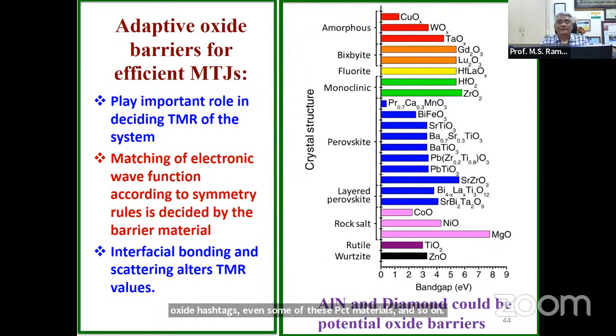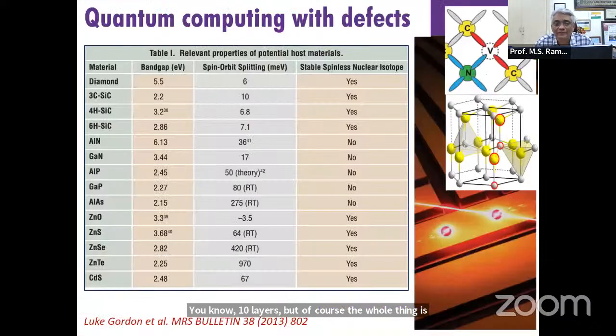This has also led scientists to think about using non-oxide layers like aluminum nitride and diamond as potential barriers. This prompted us to take up work on diamond, but it's a very, very challenging thing. While you grow oxides using a technique called laser deposition, diamond requires much higher temperatures to get into thin layers. But the whole thing has led to a new kind of research in our lab.